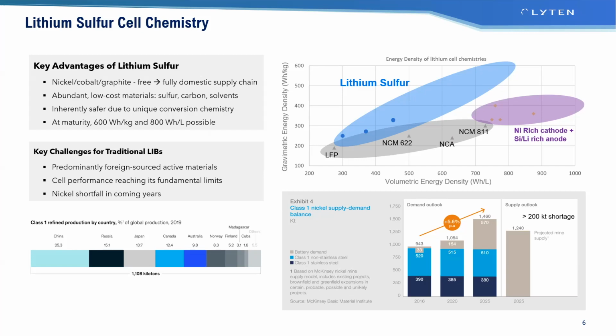Okay, and the roadmap, when you look at lithium sulfur, says, okay, great, you can hit 300 watt hours per kilo in a cell with NMC or NCA. That's kind of where you top out. If you make a lithium metal anode to go with that, maybe you get to 400, maybe 450 watt hours per kilo. Lithium sulfur has much more potential, much bigger roadmap.